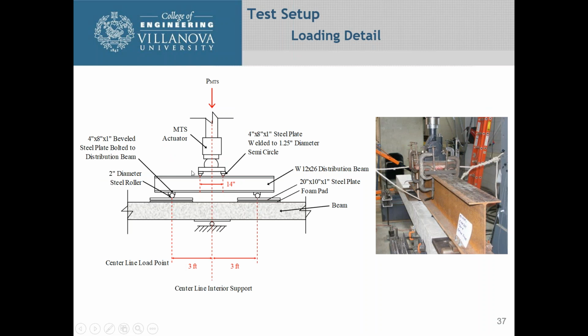This is a better picture of what the test setup was. You had the actuator and the steel beam sitting on a W12 by 26. And then those sat on rollers that sat on steel plates that were 20 inches by 10 inches to simulate the contact area of a truck tire. And underneath that, we had a foam pad between the steel plate and the concrete. And the reason for this was just so that you didn't get any stress concentrations between the steel plate and the concrete.